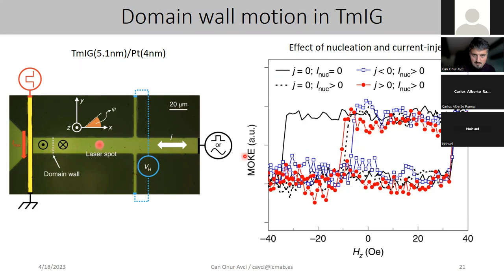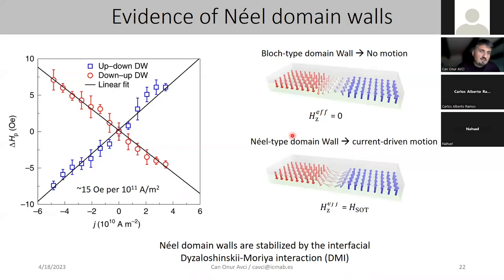And then once we inject a current after nucleation to test the effect of the current on the domain wall, we saw that depending on the current polarity, the coercivity is either increasing or decreasing. Which means that there's a certain amount of effective field or work applied on the domain wall that either makes propagation easier or harder. Once we characterize this as a function of applied current, we saw that there's a linear relationship. Which means that there's really a current-induced effect on the domain wall, which also changes sign between up-down versus down-up domain walls.